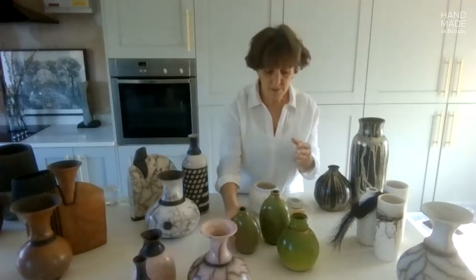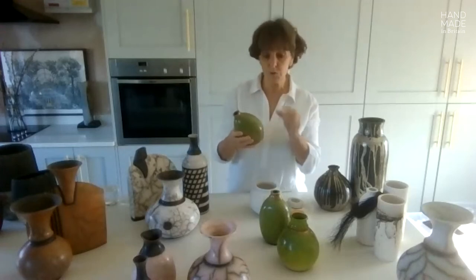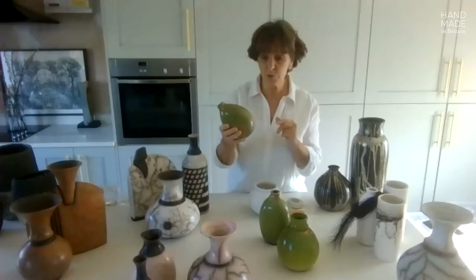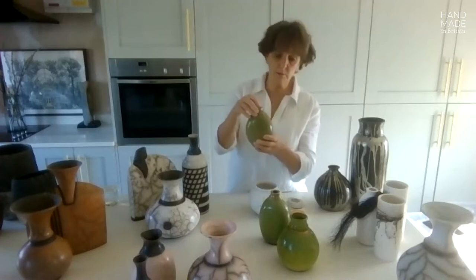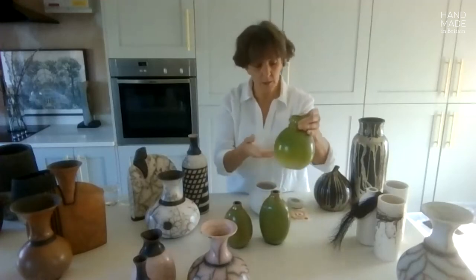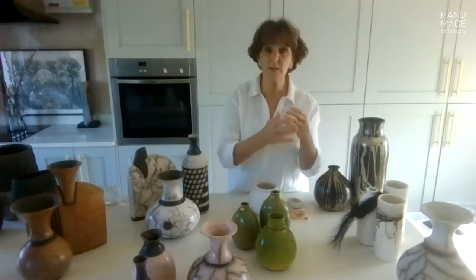With glazing I want the glaze to be fine in the raku kiln. It goes to a higher temperature — taken out at about 900–950 degrees with tongs and placed into the sawdust pits. But in this case the glaze stays on, so it's really important that I've got a good covering of glaze. With this pot I also have a nine carat gold luster ring on the pot. So the glaze firing comes out, goes into the sawdust pits and then after 30–40 minutes is taken out and allowed to cool.